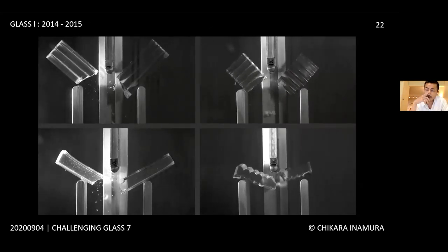Preliminary mechanical characterizations were conducted on printed glass samples. It is known that material extrusion methods sometimes result in objects with non-isotropic strengths with respect to the direction of filament, and cause the object to delaminate at the layer interface. This was also the case for our earlier prototypes, when the glass was printed without a lower thermal chamber. With the introduction of the annealing chamber, the results show fairly isotropic mechanical behavior with a nominal tensile strength of 40 megapascal, confirming that the result is a monolithic solid glass.